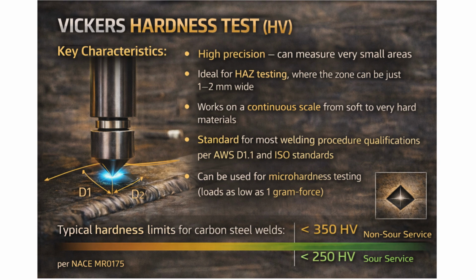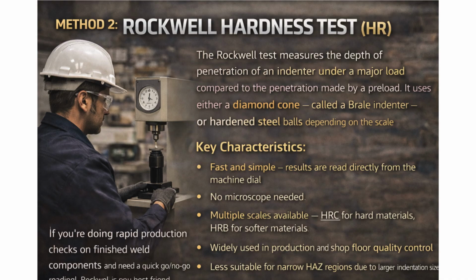Typical hardness limits for carbon steel welds: less than 350 HV for non-sour service, and as low as 250 HV for sour service environments per NACE MR0175. Method 2. Rockwell Hardness Test, HR.